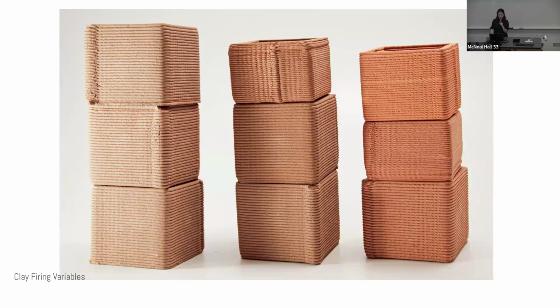A very significant piece of our research explores variable firing techniques, where we fire prototypes to sub-vitrification temperatures to test material temporalities. And we hypothesized that the kiln firing regimes could be calibrated to encode time scales into these materials, where some would degrade over a growing season, whereas some will degrade over a couple of years, and some not at all, depending on the temperature and vitrification amount.